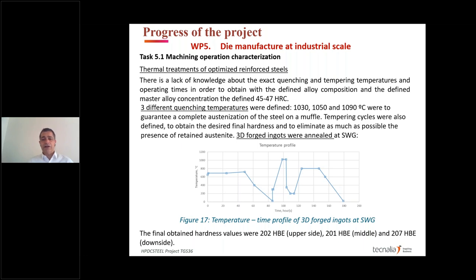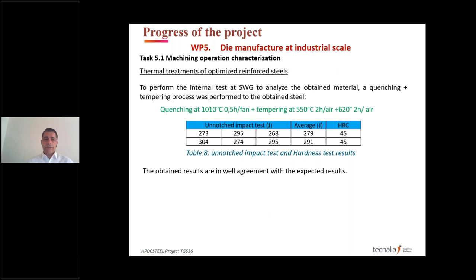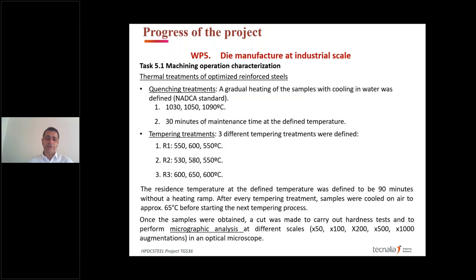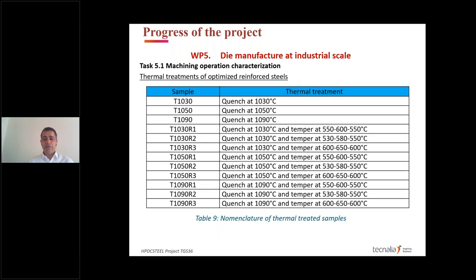Also, there was the annealing process from SWG that we have seen before, where we obtained about 200 Brinell hardness from this annealing process. Then we also have the results from the quenching and tempering process. So what we did again was trying to define a process very similar to NADCA standards with higher temperatures. We see here the quenching temperatures and the tempering temperatures from 530 degrees to 650 degrees. We made all these trials in order to test the properties.